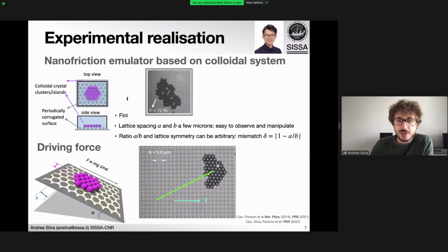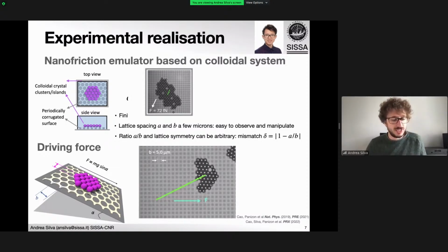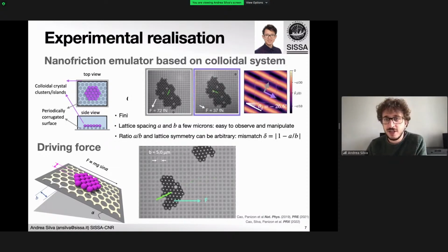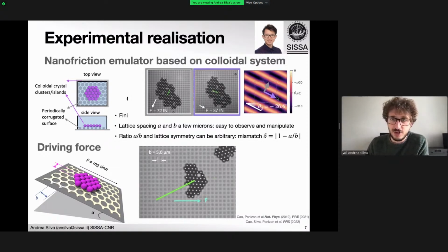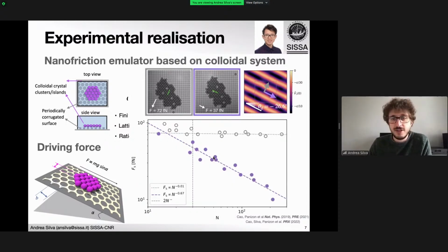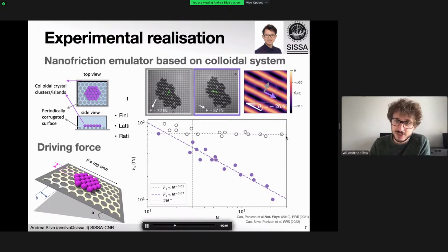If we probe the system along two directions, where we create a system that should exhibit directional superlubricity, as predicted by the theoretical model, we see that the friction along the valley and perpendicular to it nicely falls in between the prediction of the theory. So it is constant when we go across the ridges, and it scales sublinearly with size as we go along the valley.